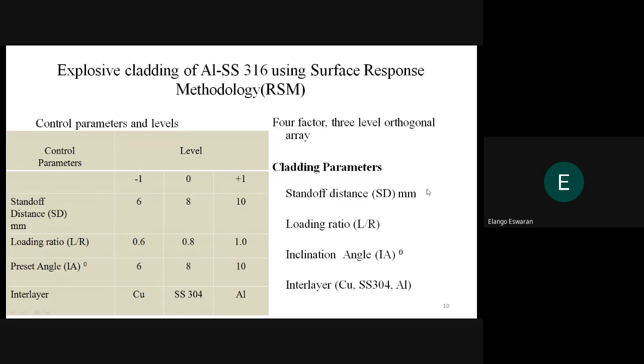In this study, the contribution of operational parameters, that is standoff distance, loading ratio, inclination angle, and interlayer to enhance the tensile strength was presented. In addition, the regression equation was developed using the ANOVA technique. Response surface methodology with the 4-factor 3-level orthogonal array design was selected and the experiments conducted as per the standard orthogonal array. The 4 parameters chosen are standoff distance, loading ratio, preset angle, that is inclination angle, and interlayer with the 3 levels. And the next one.